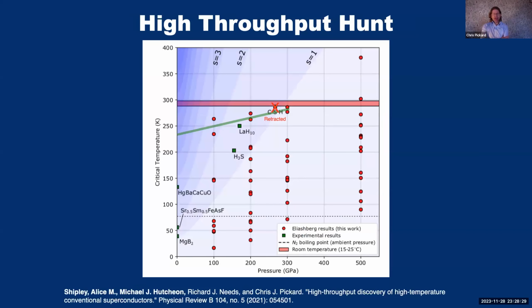So what I'm showing here is some of our efforts. There are many others across the field, but this was work that I did with Michael Hutcheon and Alice Shipley, where we did a high throughput prediction of structures across the whole periodic table for binary hydride superconductors at a range of different pressures. Each of these red dots on the plot here is a computed superconducting transition temperature for a relatively stable, certainly dynamically stable, crystal structure that we found in our high throughput searches. Often we rediscovered structures that had been proposed before, but many of them were new.